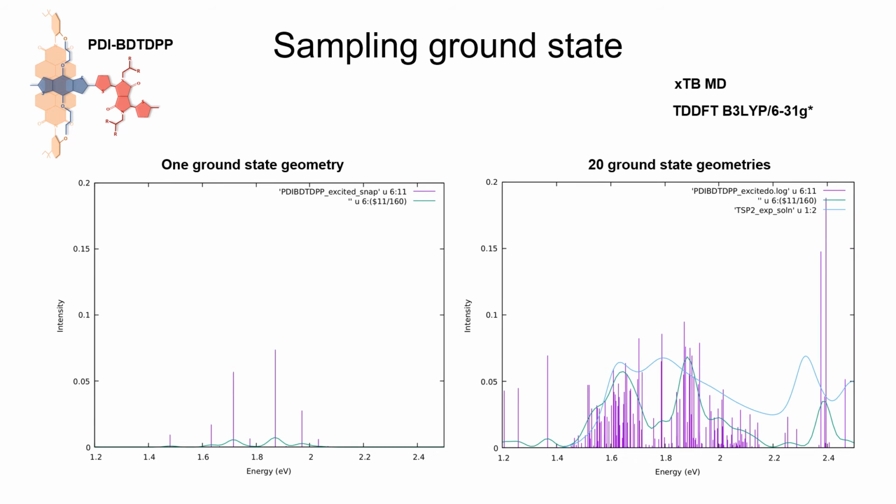Preliminary experiments and modeling have been conducted on these materials. Calculated oscillator strengths for the transitions from the ground state to the excited states are shown. Using tight binding molecular dynamics, I calculated the ground state coordinates of at least 20 conformations sampled from a thermal bath of 300 Kelvin. This gave a more accurate representation of absorption data than that from one ground state geometry.